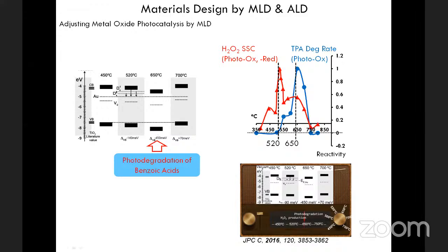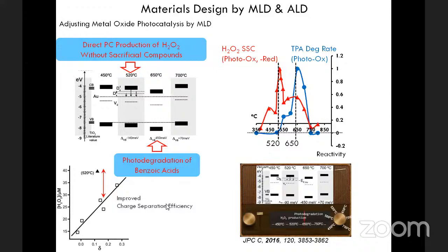While when we anneal or calcinate this material at 520 degrees Celsius, the shift is much more moderate, 140 milli-electron volt. However, we obtain two new defect states that are located just between the Fermi level of gold and the conduction band of the oxide. Here you can see defect state 1 and defect state 2. And this actually gave some good explanations of both phenomena that we observed. And the first, the photodegradation of benzoic acid, became clear because now the photogenerated holes in the valence band are much deeper, which means in redox terms that these holes are much better oxidants compared to standard valence band positioning.